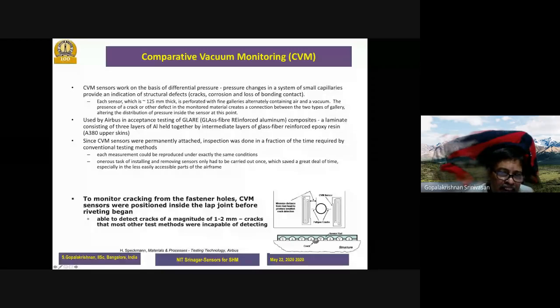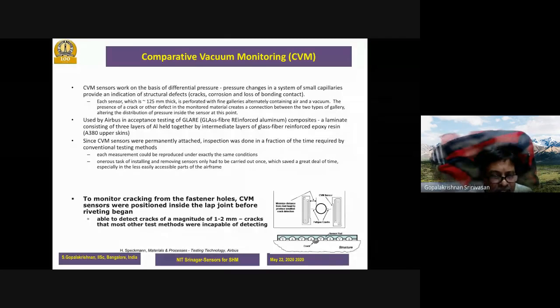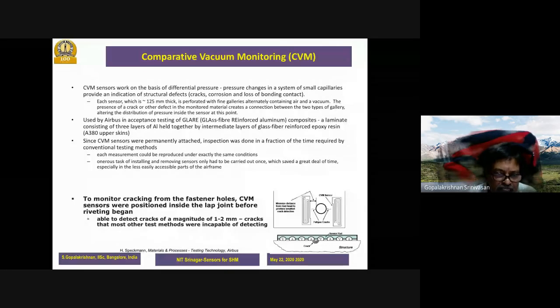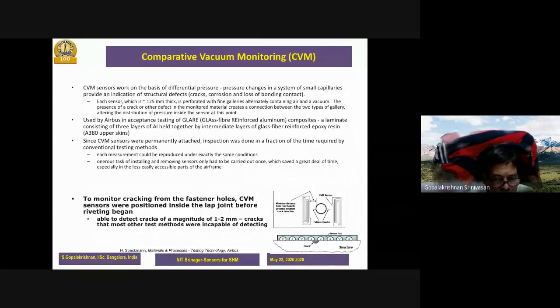For the A380, it's a new skin made of composite. They use this technique for acceptance testing of this glass fiber aluminum composite, which is what the A380 is made of. They could actually test this and certify it using this kind of simple method. Very effective, very simple, with a huge advantage of very fast, rapid inspection when the aircraft comes to the hangar. Of course, the difficulty is if you don't properly instrument this vacuum creation at the time of manufacturing, then you will miss out on regions where damage might occur elsewhere. That is something you need to take care of.